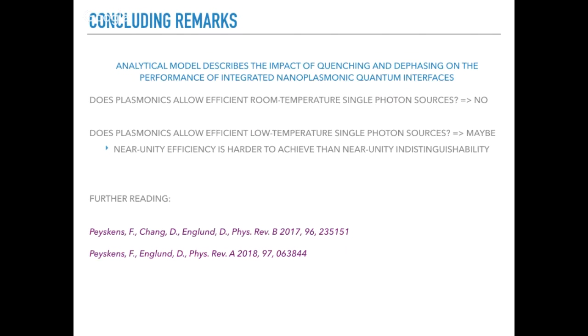And typically what people then do is use some surface chemistry, specifically for gold, thiol chemistry, where they basically have a shell around your plasmonic particle. So it inhibits the quantum emitter from coming too close, but yet you have it at a distance determined by the chemical bond. But fabrication-wise, that is very tricky. So that's why we wanted to make the exercise first: what is actually the best we can get. But even in the best possible scenario, fabrication-wise, it is very, very difficult to achieve.